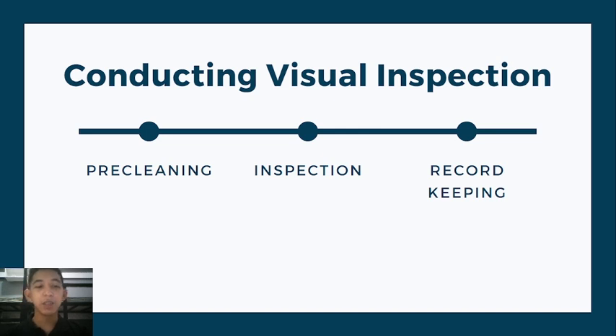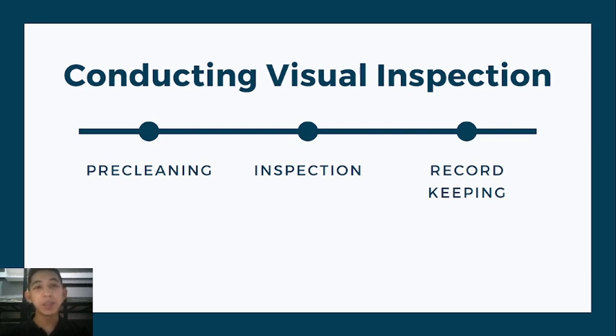Now, the areas to be inspected must be cleaned. Then we can fully and carefully inspect the area for discontinuities using optical aids as required. For our last step, record keeping — all discrepancies must be documented by routine report, photographs, or video recording. The size and shape along with the location of the discontinuity must also be recorded along with any rework performed.